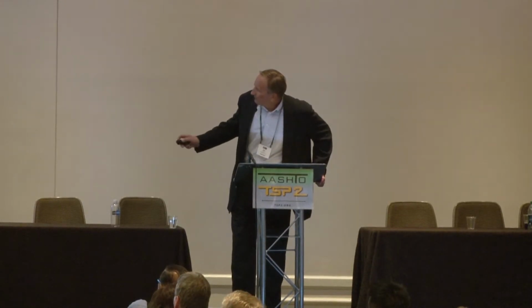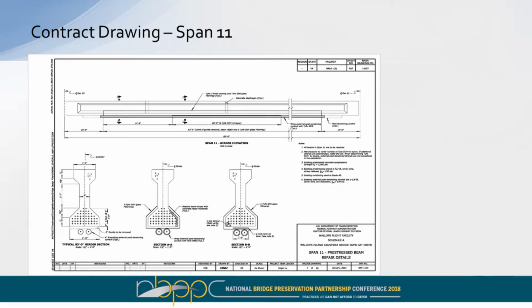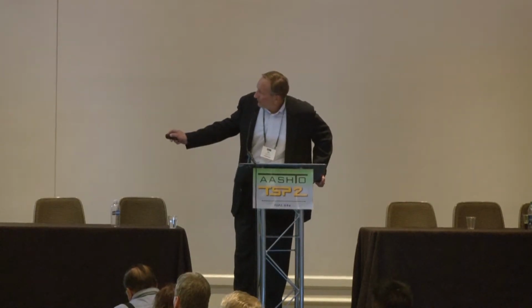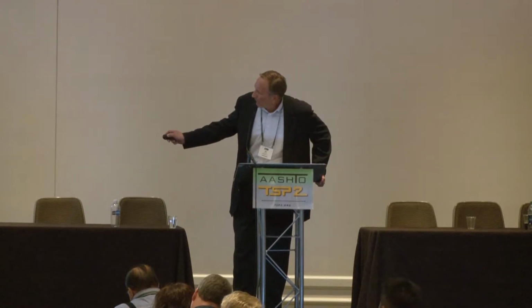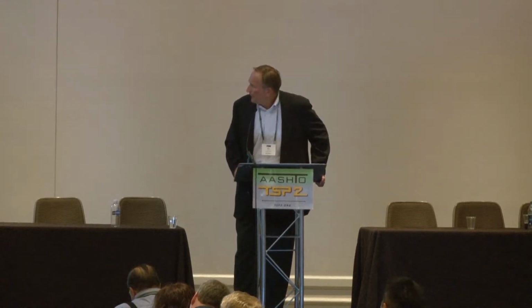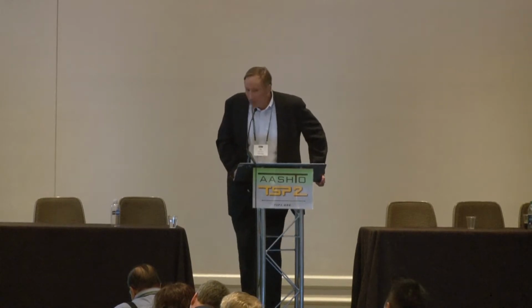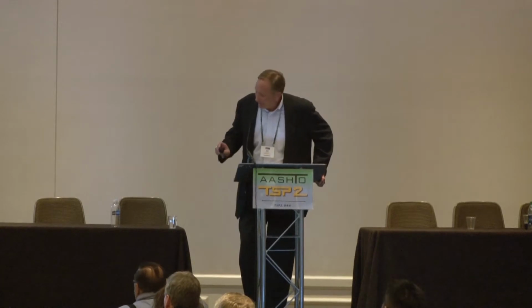So this is span 11. And you can see the same type of scenario. In this case, 2 external post-tensioning strands, which required 2 layers of carbon fiber material for flexure, and of course the glass fiber surrounding that once the carbon fiber was in place. And incidentally, the external post-tensioning strands did stay in place. We had to work around those, and you'll see that it wasn't too hard of a job to do that based on once we removed that gunite material.